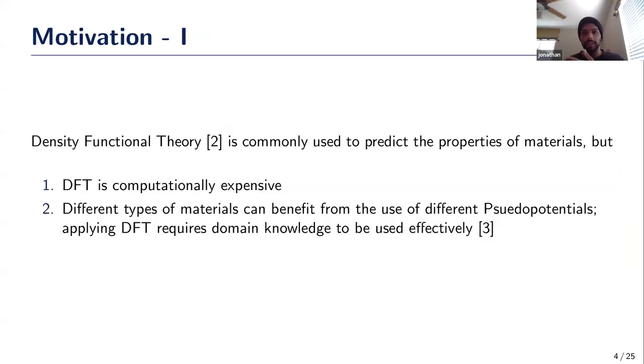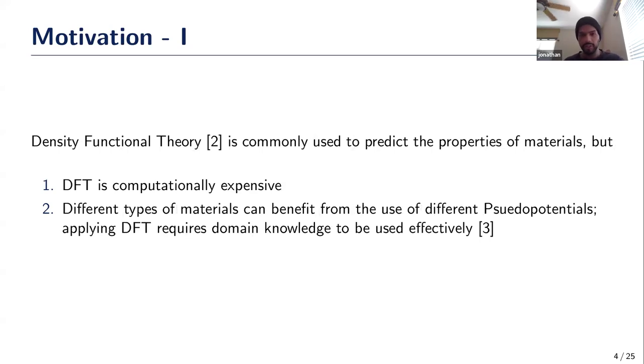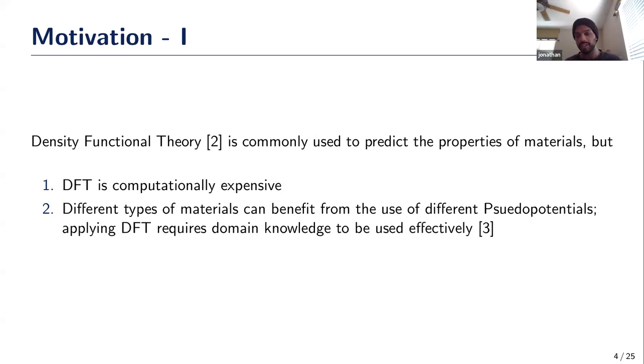Why do we want to do this? Our main motivation is that the typical way you do crystal property prediction is using density functional theory. But DFT methods have two main problems. First, they're very computationally expensive, so high-throughput predictions for large quantities of materials are just not feasible. Second, you have to use different pseudopotentials for different types of materials, and you need quite extensive domain knowledge, making DFT less accessible than machine learning methods.